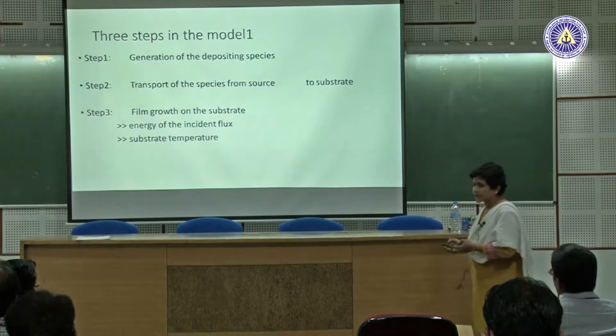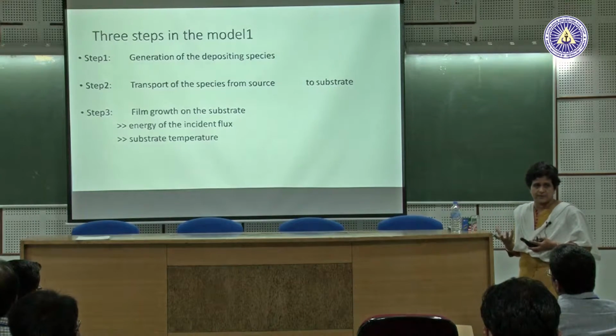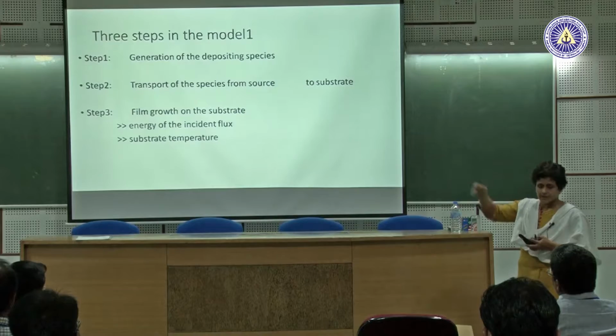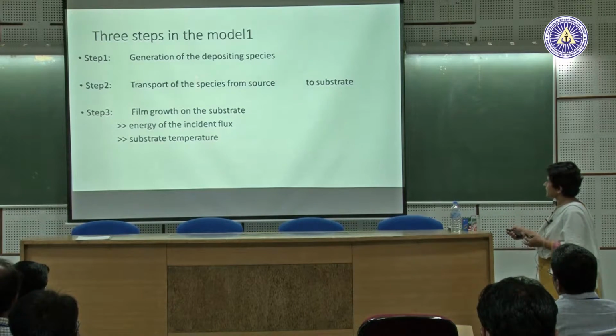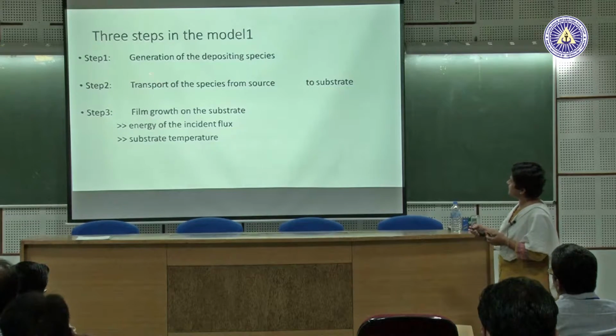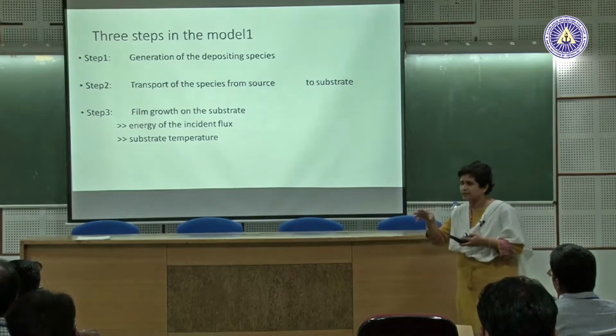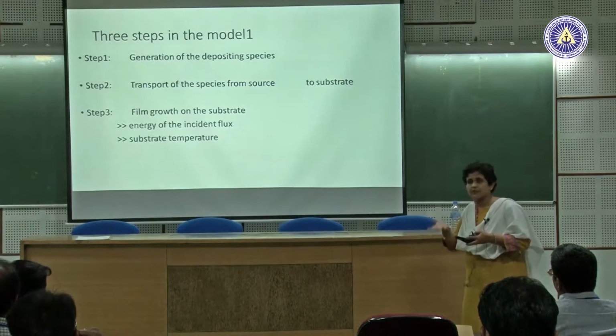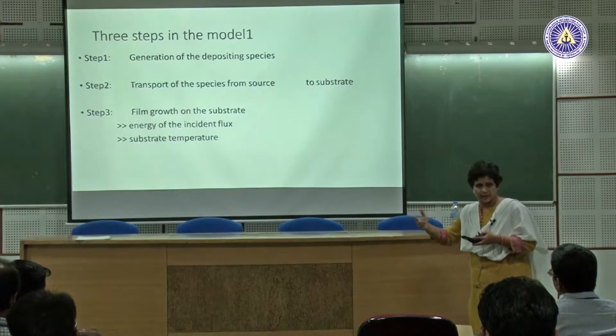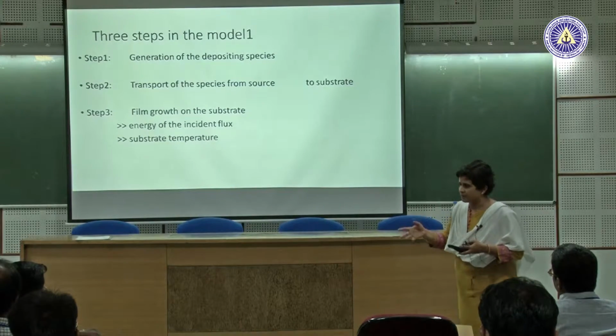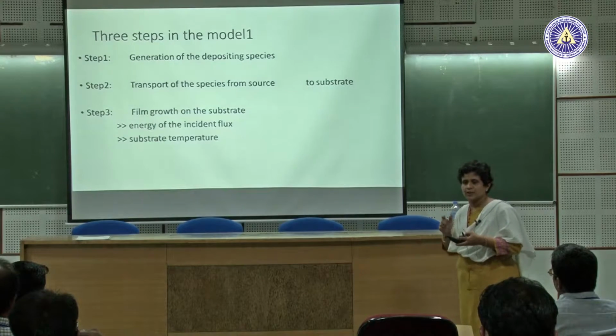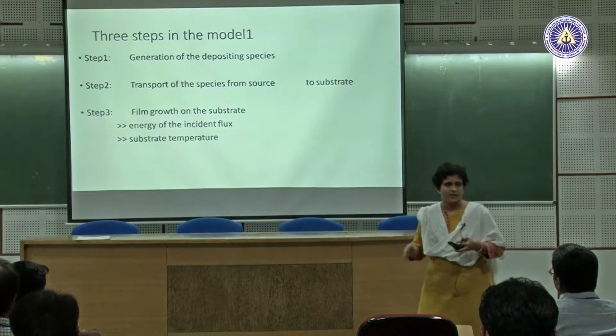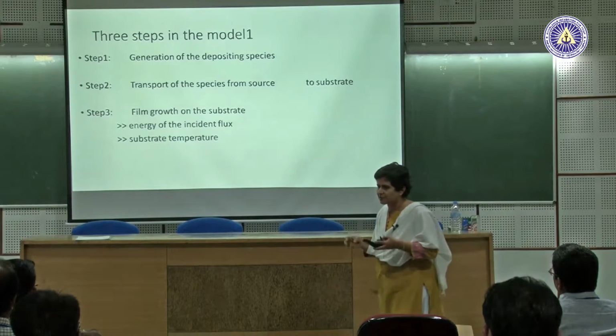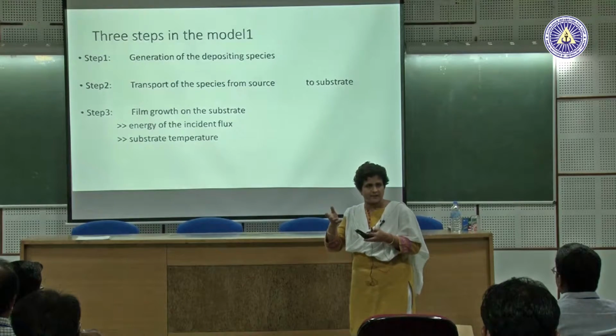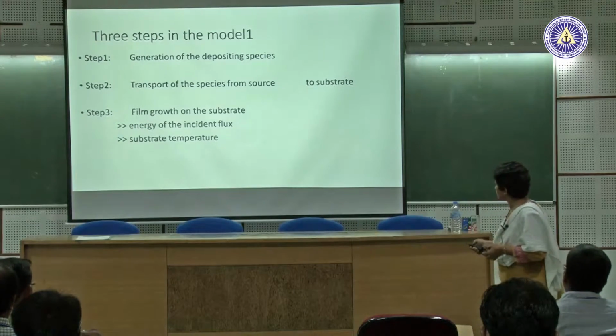The second step is the transport of that species from the source where you created the species to the substrate where you will form the film. Okay, so, that is the second step in this thing, and that itself can have many variations, right. So, first step can have many variations, second steps can have many variations. You can insert a gas while the evaporation is taking place, you can use plasma while evaporation is taking place, and again that is another variation into the technique. So, I was mentioning there are a large number of techniques, it is because of these variations. So, every time you make a variation, you give it a new name, right. So, if you put something in the step 2, you call it reactive evaporation rather than evaporation, right. So, do not get confused with many names, it is basically same technique a little bit modified. If modified is step 1, step 2, step 3, you can have a different name that goes with it.